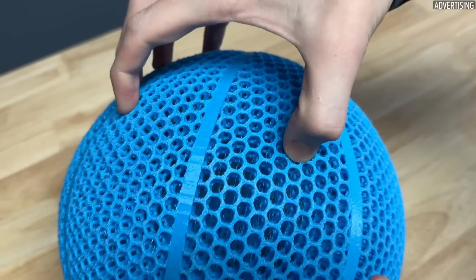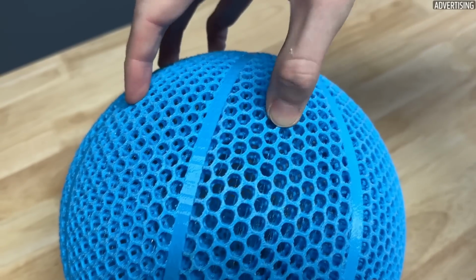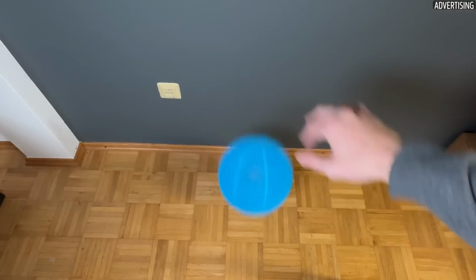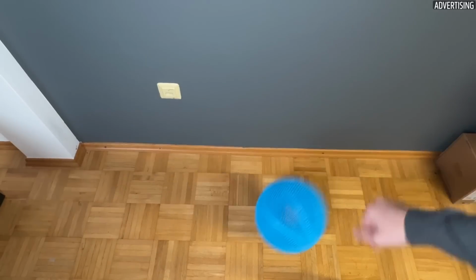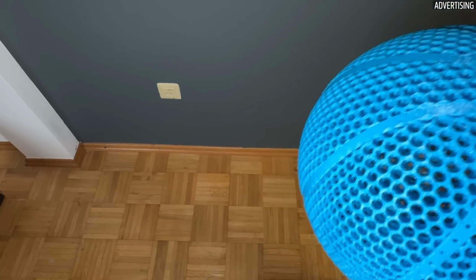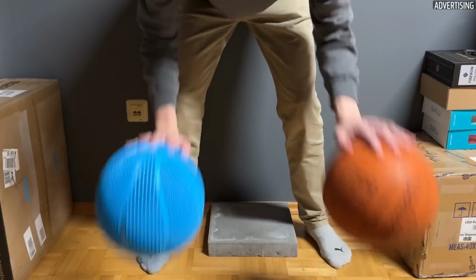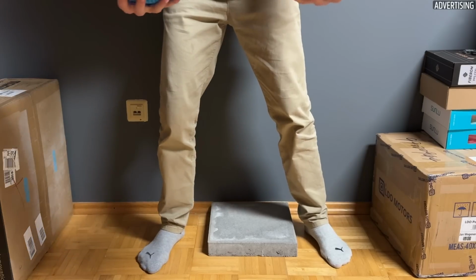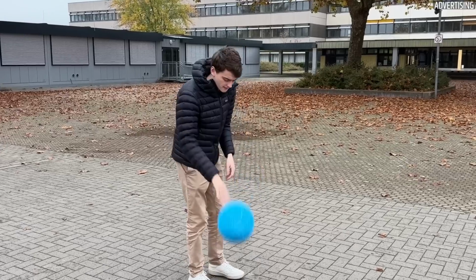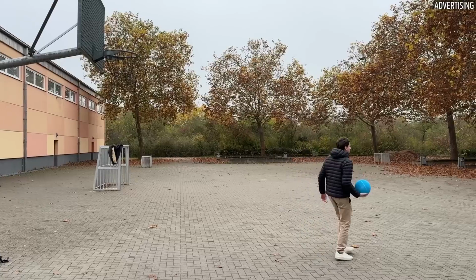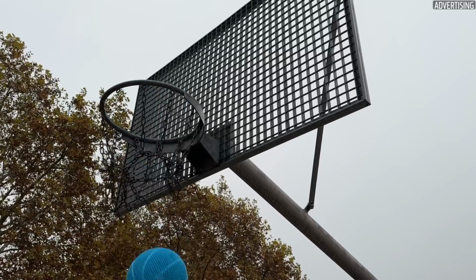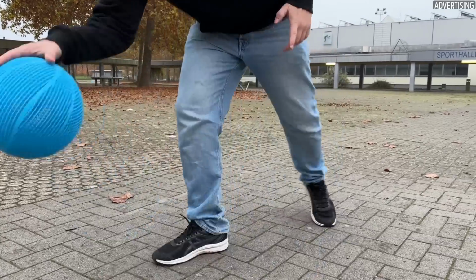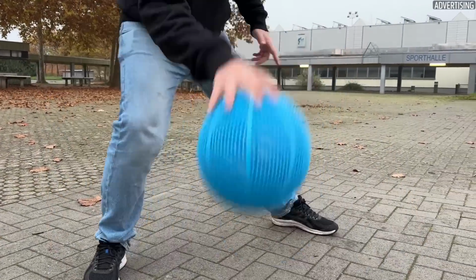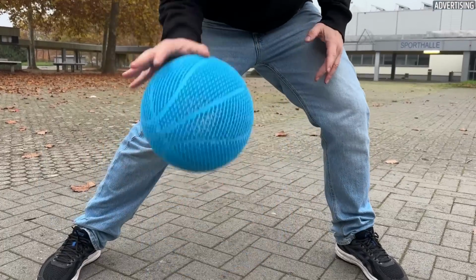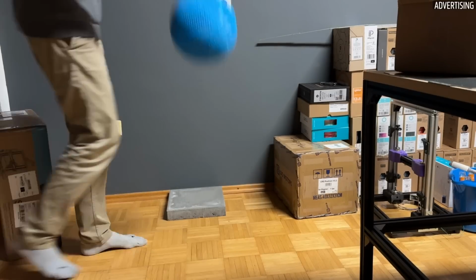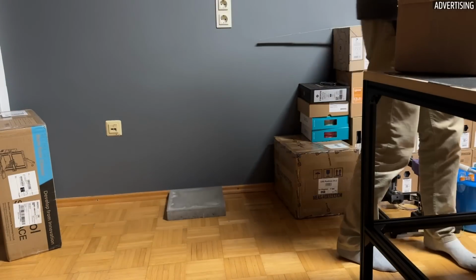The ball feels hard and, unlike my small test model, cannot be bent. At first, the bouncing is a bit unusual because you don't expect, let's call it a piece of plastic, to bounce that high. Overall, the bouncing behavior is very similar to a conventional ball, even if it bounces slightly less high. I also took the ball to a court, and the throws feel relatively natural. I noticed that the printed ball is quieter. The typical bouncing sound is duller and not as loud, especially outside on concrete. I bounced the ball around for several weeks and so far it is holding up without damage.